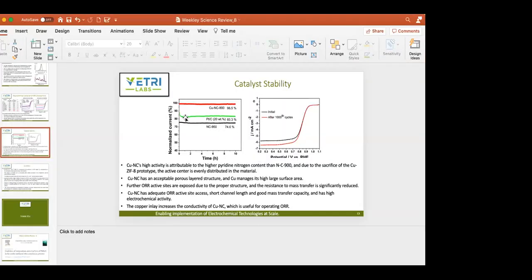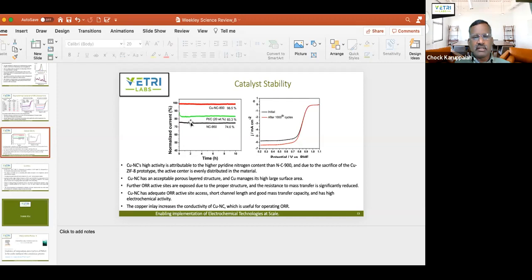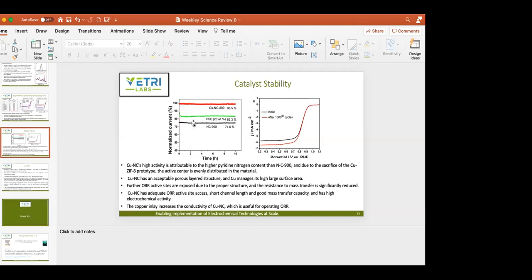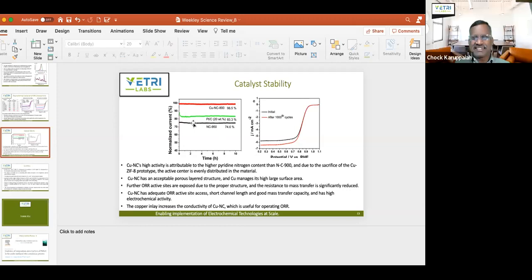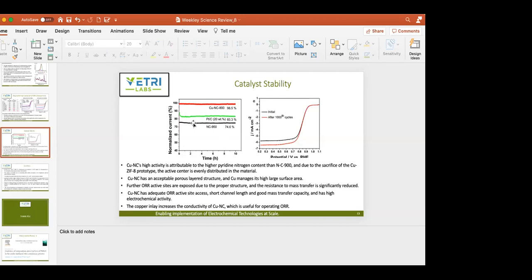But we can see on the XRD data, I can actually share the screen, the catalyst stability data. Actually, they see a change over here on the platinum side in about 30 minutes. Within less than 30 minutes, they see this drop. When you look at NC 900, I don't see anything. It starts at about 75%. That's what I didn't understand, how they calculated and how they attributed the stability of 75%.